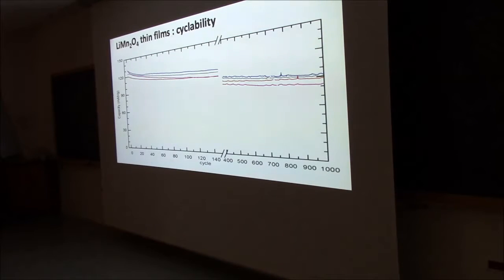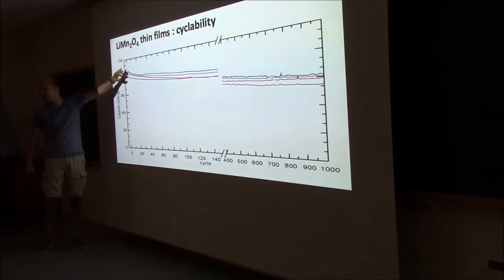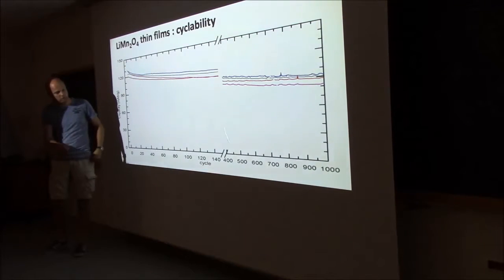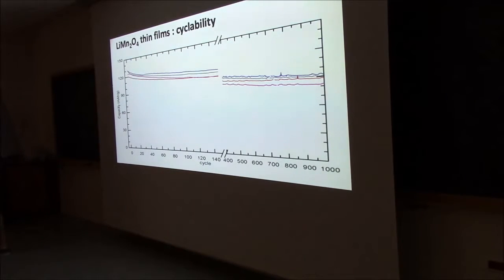And then we started cycling, of course, for a very long time, so we cycled it up to 1,000 cycles. This is from the beginning. These are 4 similar samples, all grown at a 100. So with these pyramids, you can see they're pretty similar. So there is a break here, but you can see, of course, it drops over time, but the drop is not that much. I told you for a lot of battery systems we want to cycle them about 300 times and then we're pretty happy. So if you do that, I think the numbers are pretty reasonable. And this material normally is thought of as promising but so problematic we should not do that. And I think what we show is that if you control your synthesis in a way that you control the real interface towards the opposite material or the electrolyte, then reactions are not happening and you can still use these materials in an interesting way.